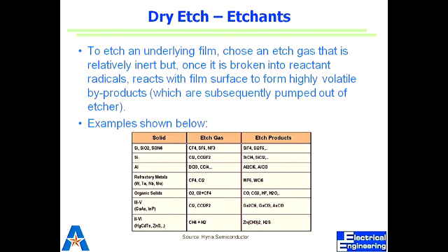What happened to the C in CF4? The fluorine became SiF4 with Si. What happened to the carbon of CF4, tetrafluoromethane? Where does it go? Actually, carbon also reacts. Sometimes we introduce oxygen. If we introduce oxygen, carbon forms CO or CO2, and they are also very energetic, and the etch rate is increased. So that's what I was going to discuss. You will come to know how that C is actually used.